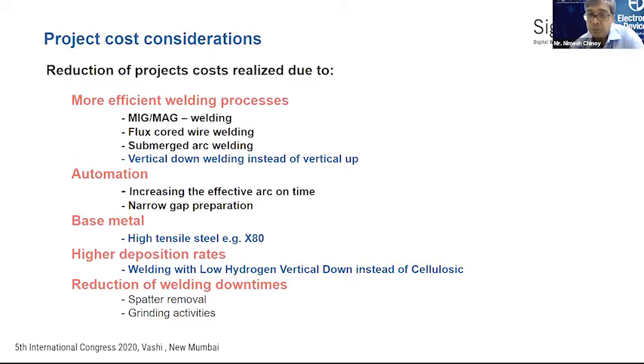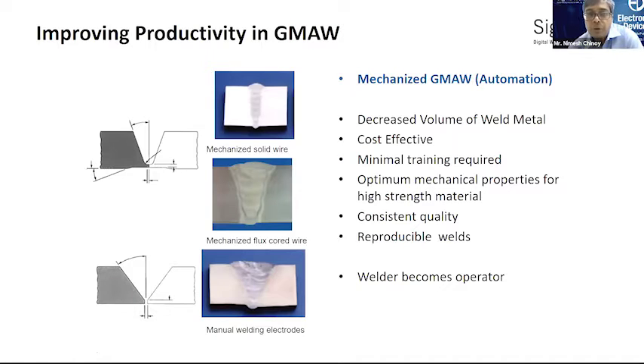Then narrow gap preparation, which Rajshekharan sir covered, means that if you are covering a lesser amount of area, you will be putting in a lesser amount of material and covering a larger weld place. The type of base metal you choose, if it's high strength, needs lower thickness, higher deposition rates, and reduction in welding downtimes due to spatter removal or grinding activities. If you want to improve your productivity in GMAW or MIG welding applications, you can move to mechanized MIG welding.